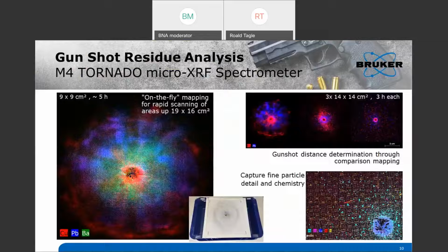Yeah, so in this case we only showed these 3 elements, but since we are using energy dispersive detectors and also the hypermap functionalities, we do have the whole spectra for all these elements, and our spectra usually go from 0 to 40 keV. So all the elements which are in this spectral range, and these are pretty much all the elements from sodium on, can be displayed. Basically, after you save the data, any element that was detectable at the time of the measurement under the given conditions can be displayed after the measurement.